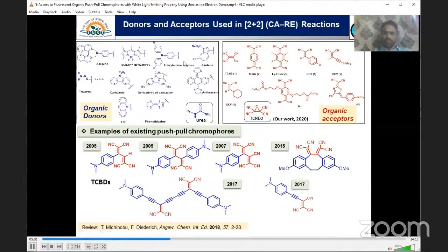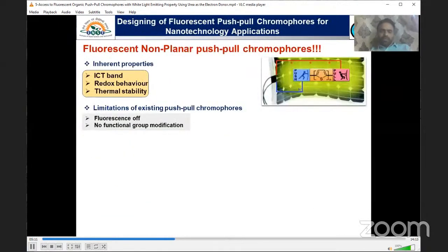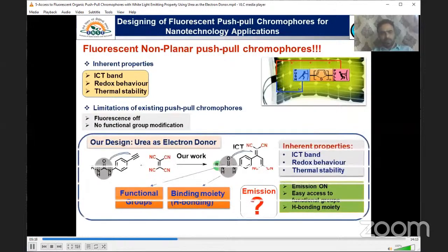This is the urea which we added in the donor part, and this is the acceptor which we added in the acceptor part. These are some of the push-pull chromophore systems which have been reported over the last decade by the Diederich group. So what we did is, since all these push-pull chromophoric systems have some limitations and some properties too. The inherent properties of the push-pull system, which are already known, are that they are stable, they have reversible redox behavior, and they have a stronger ICT band, but the limitation was that they were not fluorescent.